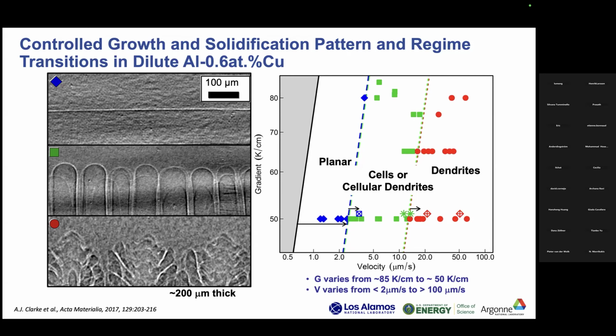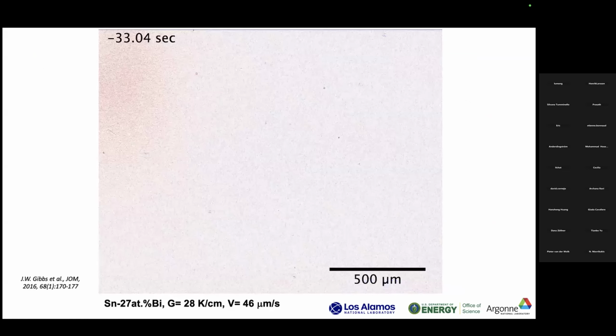And so the thing we kept coming back to was convection in the melt. And I'm going to show you an example that I hope kind of convinces you of this. So the work I was showing you was on a very dilute aluminum copper alloy, which doesn't have great contrast in the synchrotron X-ray imaging. But I'm going to show you an example for tin bismuth, which shows it a lot more clearly, just to illustrate the point. So this is actually going to be a false-colored synchrotron X-ray movie with top-down directional solidification.